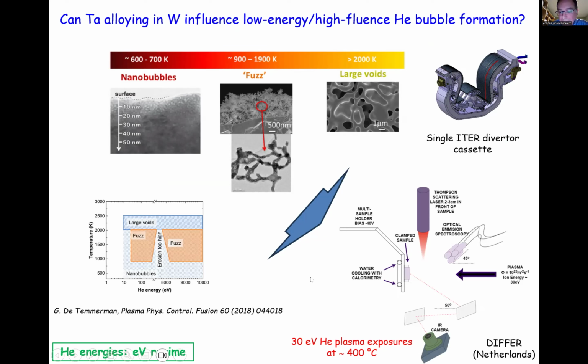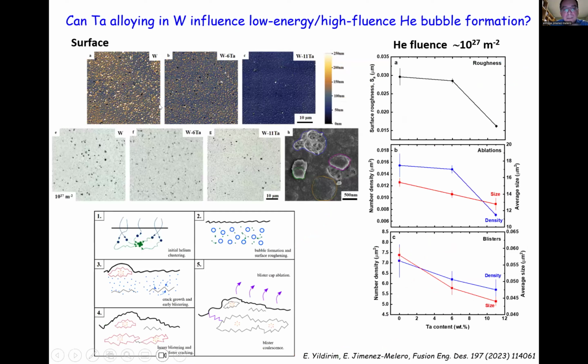So as an example, what we did is to put tungsten and tungsten-tantalum alloys at the DIFFER facility, where we irradiate them or expose them to low energy plasmas at 400 degrees, and I'm going to show you what we found out as a behavior. So you can look at the surface with laser scanning microscopy or simply optical microscopy, and this is what you see for tungsten or tungsten with a little bit of tantalum.